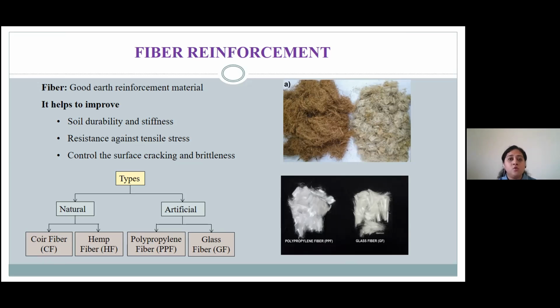It was observed that, using these fiber lengths, when we reduce the fiber length to less than 10 millimeters or greater than 40 mm, it demonstrated a low contact area, and it was difficult to achieve higher pull-out intensity during the loading.